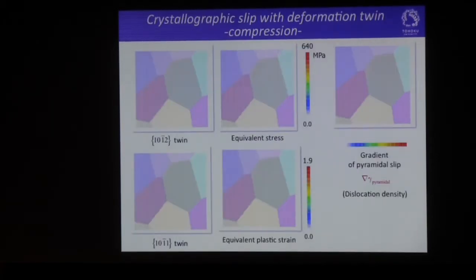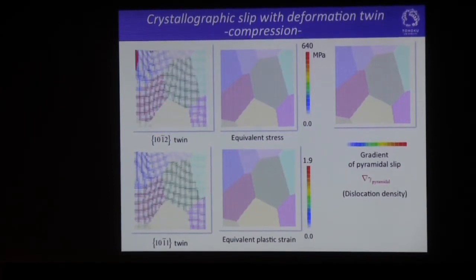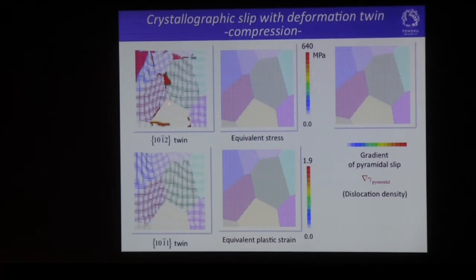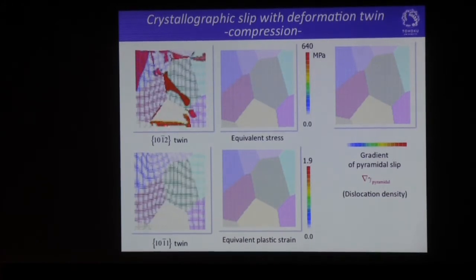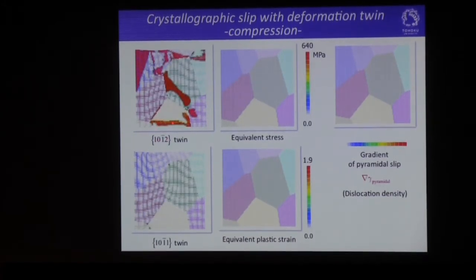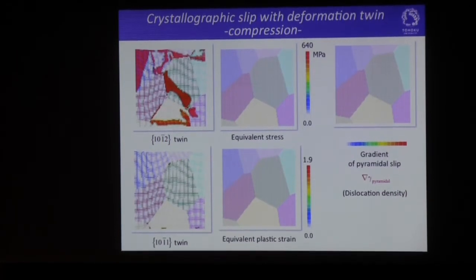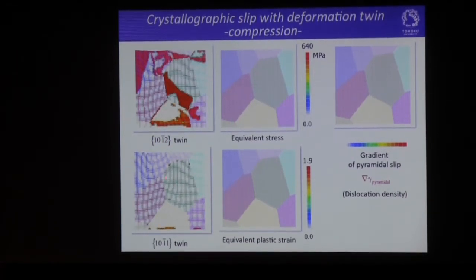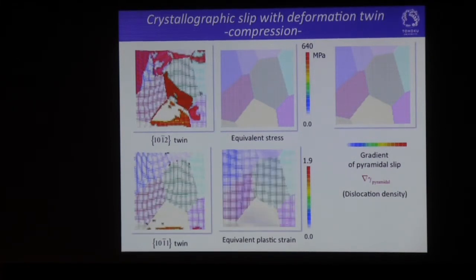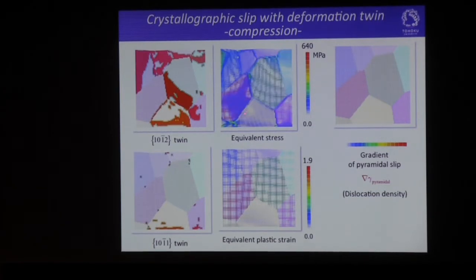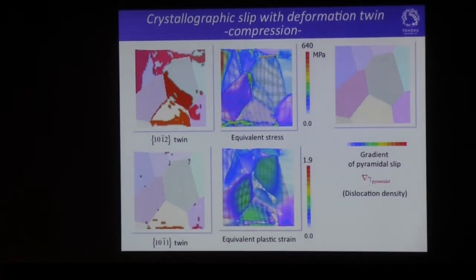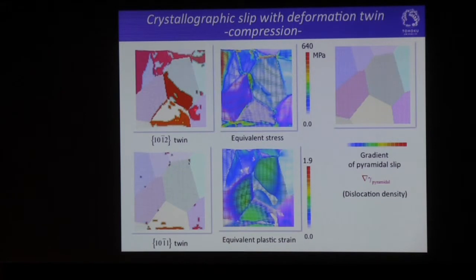Here shows a numerical example under compression. This is the typical distribution of the deformation twinning. As you can see, the {10-12} twinning is more likely to be active compared with this deformation twinning. And also, during this deformation, we could have this kind of microscopic stress distribution together with the plastic deformation like this. As you can see, in the region of the twinning deformation, we could have this kind of small value of plastic strain.